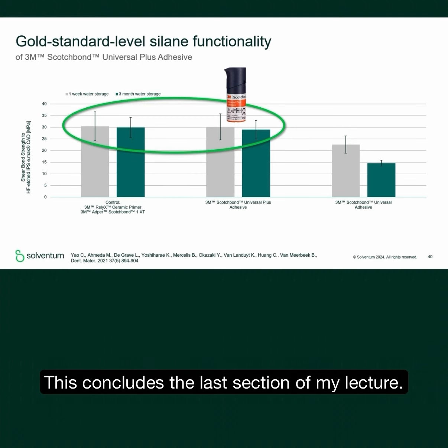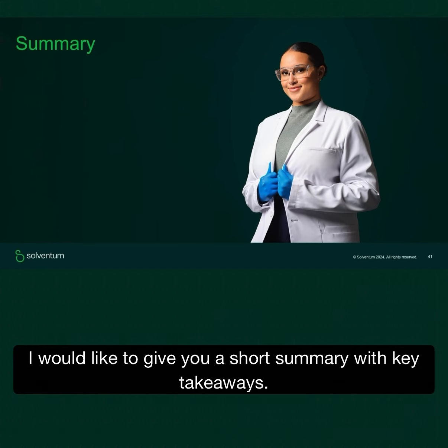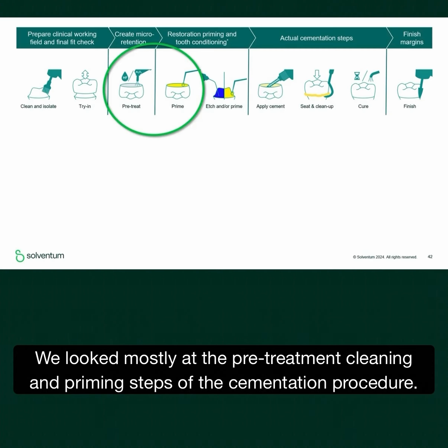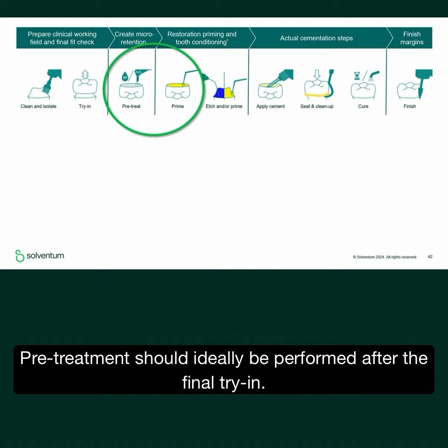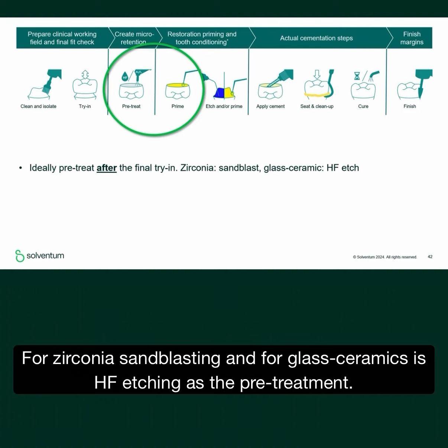This concludes the last section of the webinar. I would like to give you a short summary with key takeaways. We looked mostly at the pre-treatment, cleaning and priming steps of the cementation procedure. Pre-treatment should ideally be performed after the final try-in. For zirconia it's sandblasting, and for glass ceramics it's HF etching as the pre-treatment.